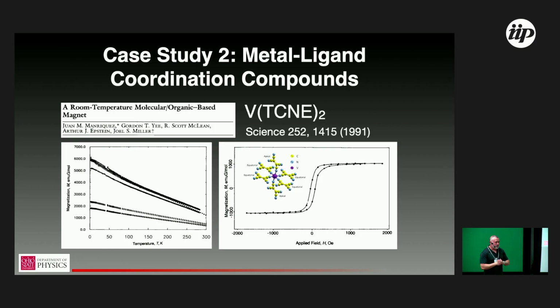And I'll come back to the structure in a bit, because one of the stories of developing this material is that it's taken quite a long time to get a handle on what that structure actually is, for various technical and fundamental reasons. But in this initial demonstration, the key point here is the temperature scale again goes up to room temperature. This temperature dependence is very strange. I wouldn't spend too much time worrying about the fact that it's linear. I think this is again a sign of disorder.